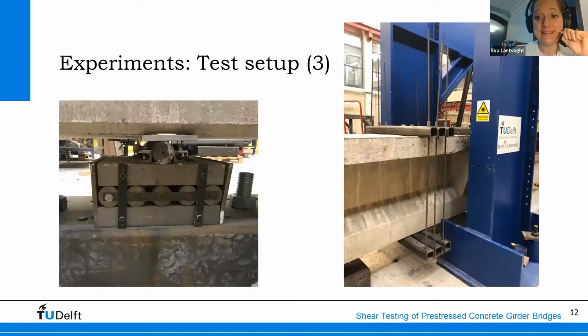Some details of the test support. Here you see the detail of the support, and here, since the specimens were sawn, we wanted to avoid the pre-stressing tendons to pull in and cause a splitting failure on the sawn edge. So we provided vertical pre-stressing. So these are Dywidag pre-stressing bars to apply an actual load on the cross section to avoid that failure on that side.